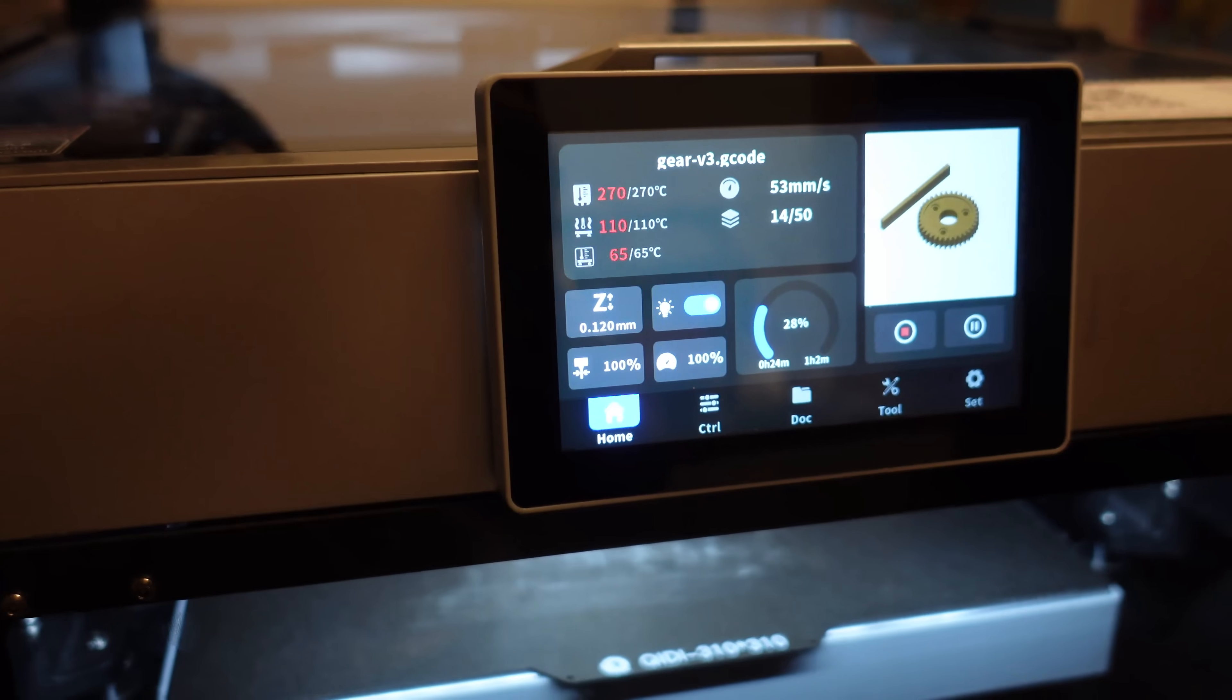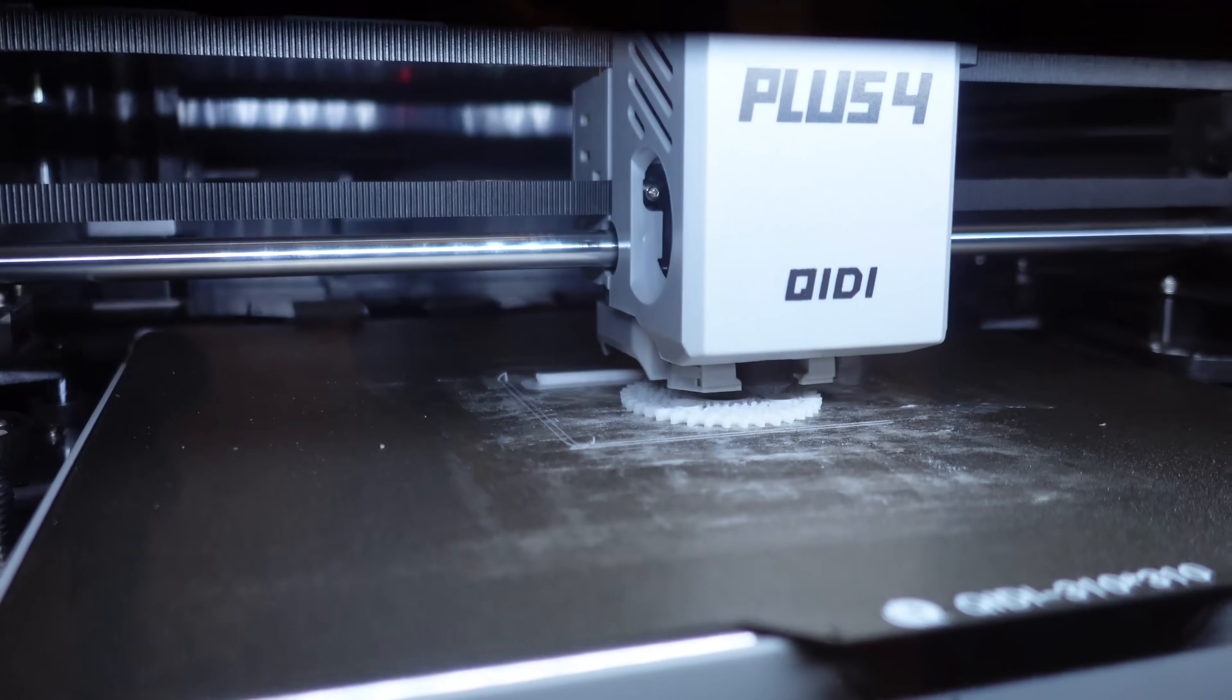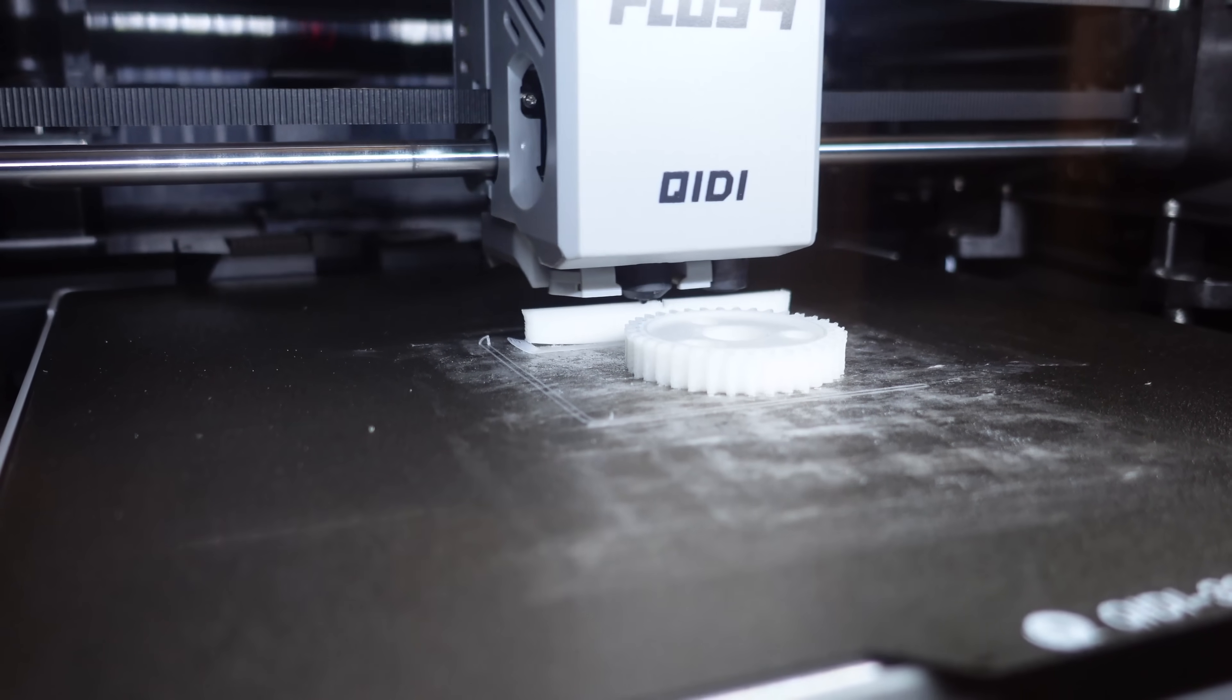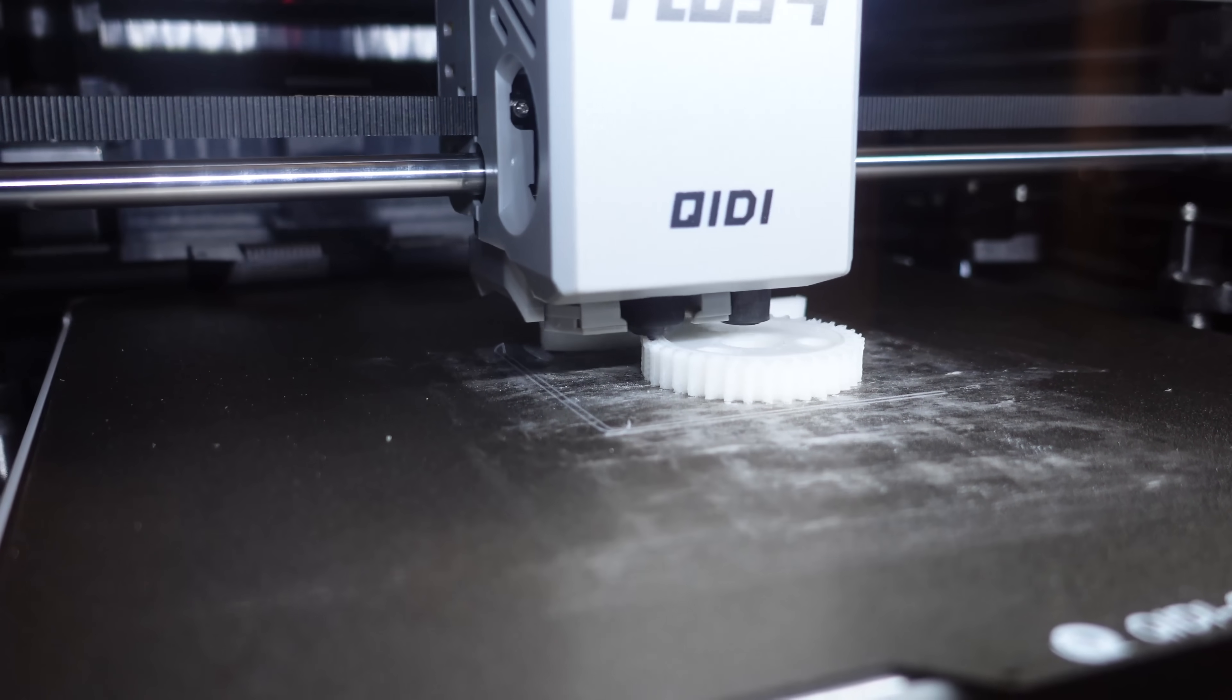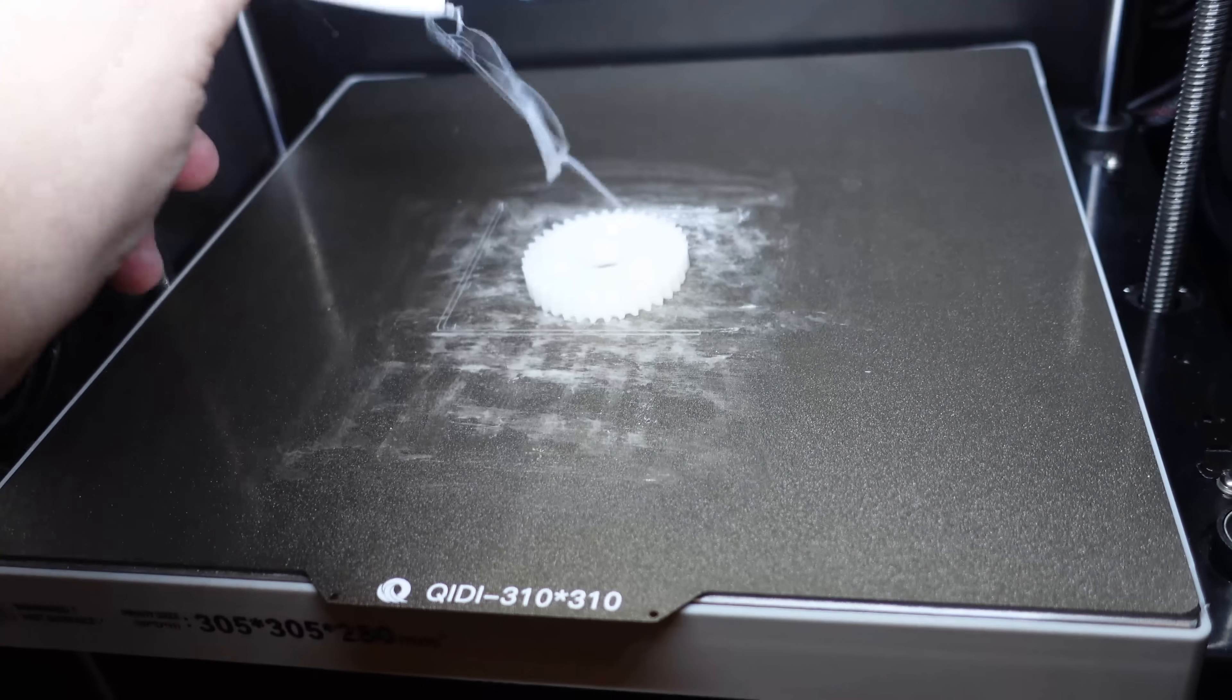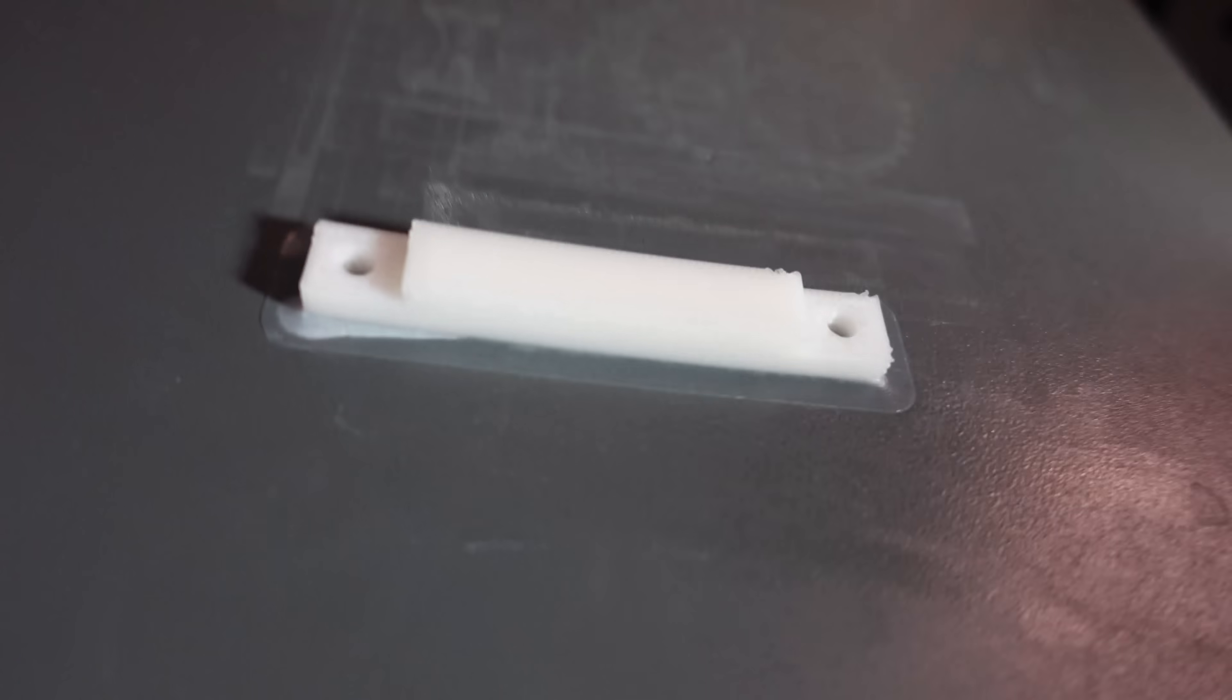I decided to give it a try on the Qidi Plus 4. I tried to use the same settings here, only the temperature inside is 65 degrees Celsius, and I am using the brim only on the ISO test object. Gear will be printed without brim. It's almost finished, but looks like I have similar warping like with the X1 Carbon when I used the brim. But the reason for this is weaker bed adhesion with the textured PEI sheet compared to the engineering plate. It's finished few seconds ago and I want to show you I wouldn't be able to remove it immediately on the X1 Carbon, but here it's removable. Again I want to check my theory. This test object is for the wearing test and I am using similar settings like with that critical printing on X1 Carbon. Object is almost finished and no sign of the warping. But now let's check the bed.